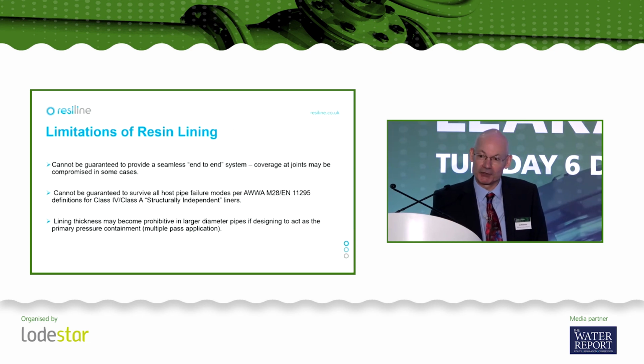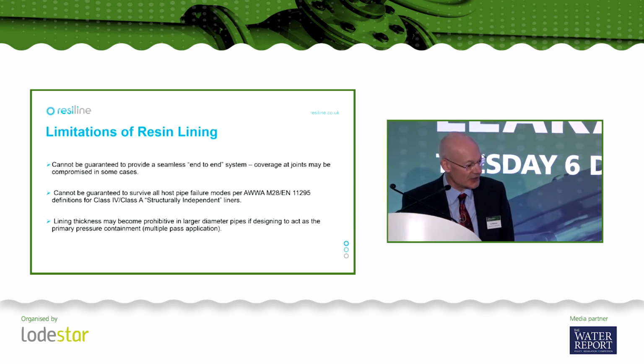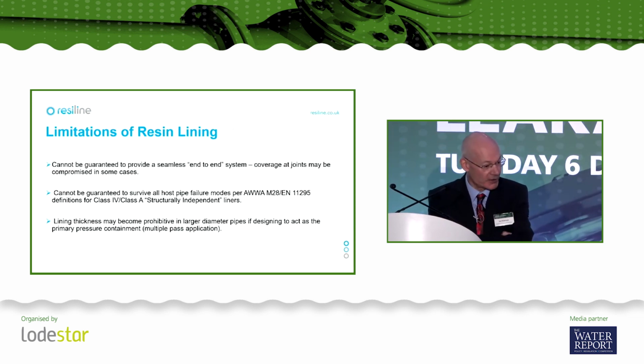Okay, so that's everything that's good about resin lining. So what about some of its limitations? Well, the first thing is that resin lining cannot be guaranteed to provide a completely seamless end-to-end solution. So it may or may not survive catastrophic failure of the host pipe. And the lining thickness required could become prohibitive in larger diameter pipes, especially if you're looking at designing the lining to act as the primary pressure containment.